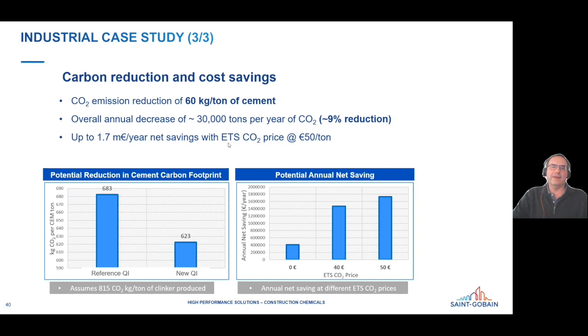So in the left plot here, we're seeing the CO2 footprint directly. This is how many kilograms of CO2 are released for every ton of cement that's made. For their original type 1 cement, it was 683, and that was lowered to 623 by the addition of the pozzolan. And this is the savings in euros per year that they're able to get from that. The savings comes primarily from the fact that in Europe they are paying to emit CO2. So they're paying about, in this case, I believe 50 euros for every ton of CO2 that's emitted. So when you allow them to emit less CO2, it's a direct cost savings in Europe.